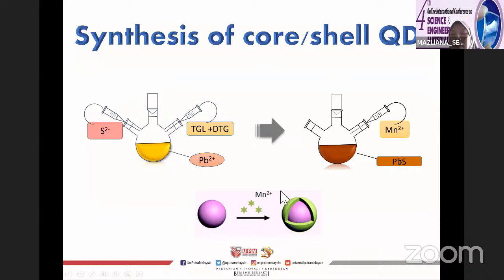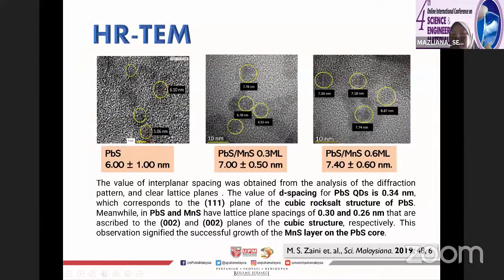This cation exchange is quite famous. You just need to introduce one type of precursor in order to get the shell layer. By increasing the amount of the manganese solution, we can increase the thickness of the shell.